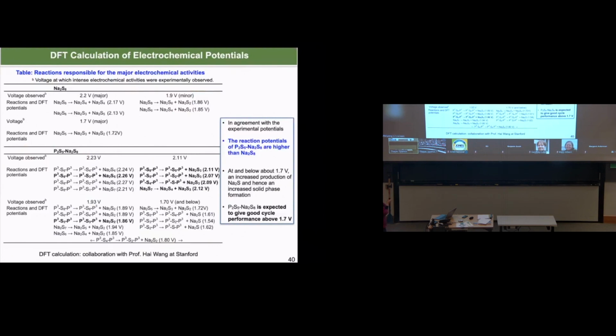This is based on DFT calculation. We do compare the theoretical calculation with the experiment. We do see that, based on theoretical calculation, the reaction potential of this complex catholyte does have a higher potential compared to the conventional case.